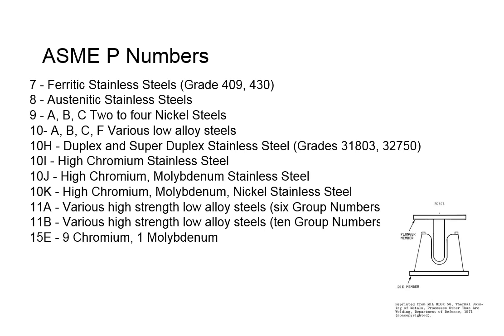I used to work at an outfit where we did a weld procedure on like 12-inch thick duplex stainless steel, and we couldn't get the interpass temperature above a couple hundred degrees, so it would take us days to do the weld coupon. I'm not kidding. It was a thick material, and the welders would just sit in there until it cooled down again. All right, run another pass.